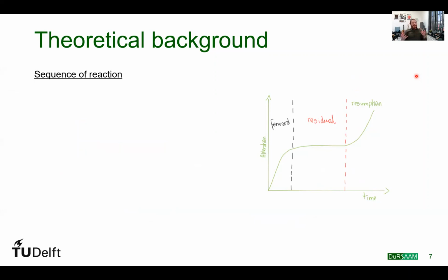Later on, these reactive species that were initially released will combine with each other to start forming some activated complex materials. This creates a sort of passivating layer on the surface of the precursor particles, which will hinder further dissolution for a period, and that is called the residual period.